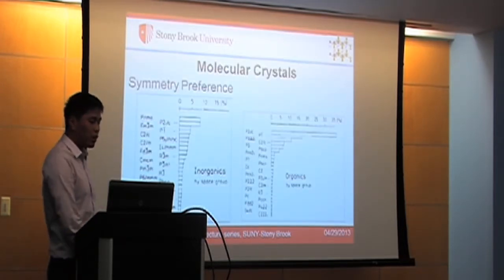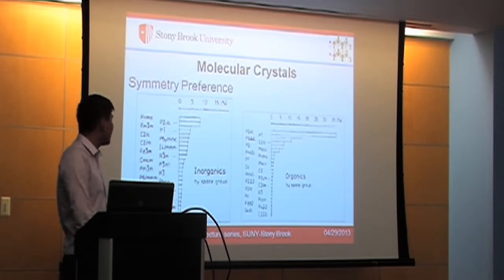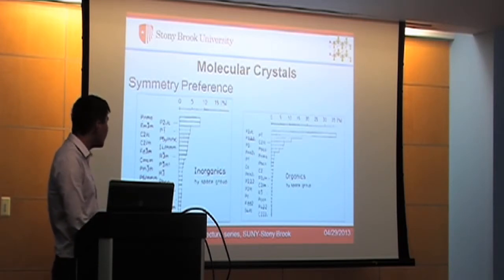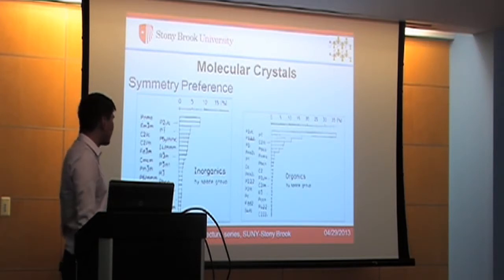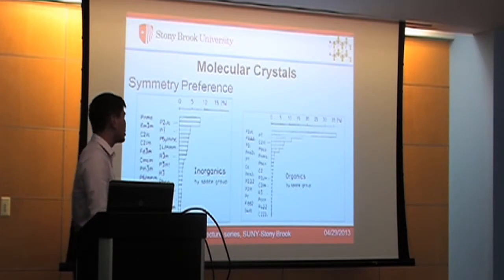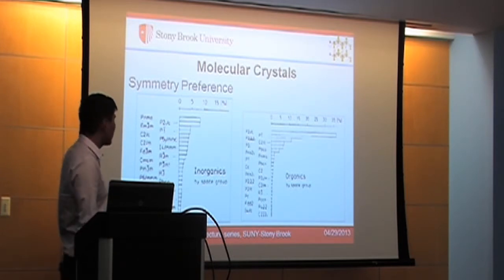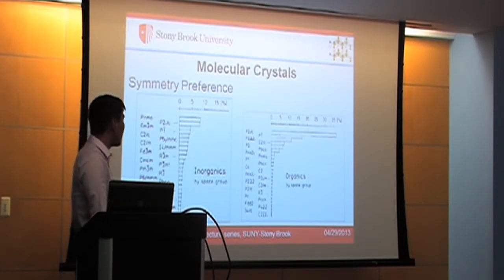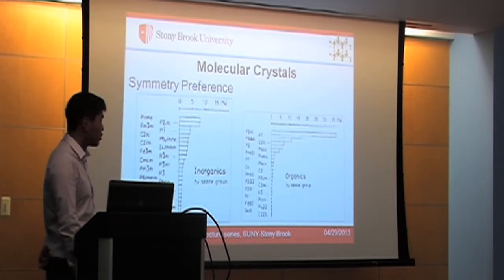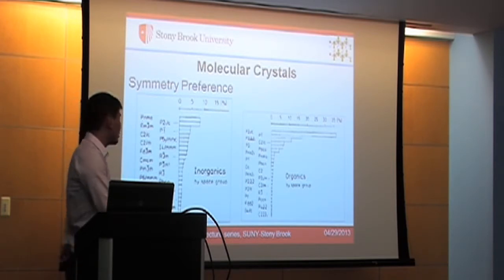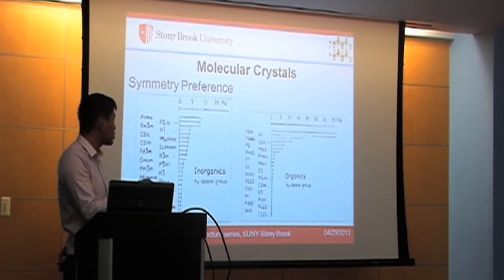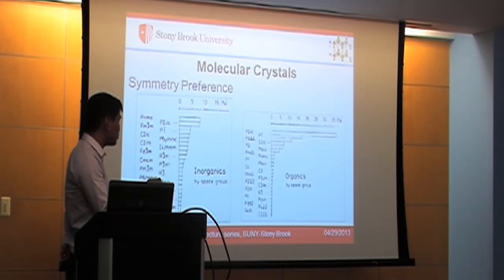Another important feature of molecular crystals is that they have a pretty uneven symmetry preference. Just to compare the symmetry distribution of inorganic and organic crystals, we found that organic crystals usually prefer some particular space groups very much. So it indicates that when we perform our search, we don't need to scan all the possible configurational space. Instead, we just need to focus on these particular space groups which are favored by nature.